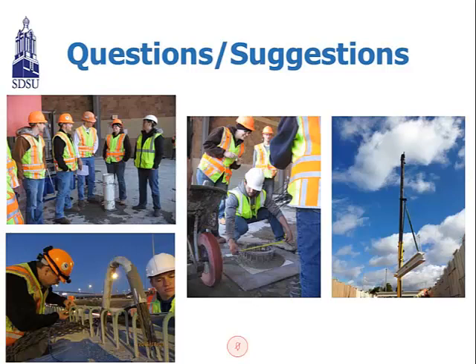Okay, I think I had one other question. Transfer length, I had not heard that before. Was that pretty challenging to do? How did you perform that test again? Well, actually, transfer length we measure by strain gauge readings. Transfer length is typically used for the design of the prestressed girders. So if the transfer length is higher than the AASHTO limit, we are concerned about it. That's why we compare the measured transfer length versus the AASHTO ACI. The good thing is both the SCC girder and the CC girder are conservative relative to the AASHTO ACI.